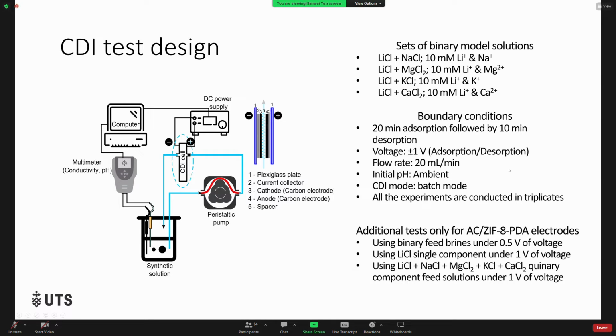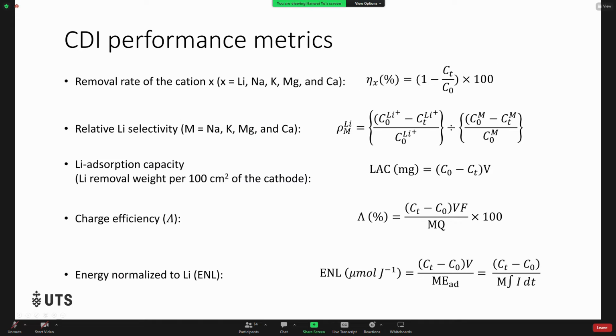These experiments are based on all 3 electrodes, and the additional tests only for the modified electrode are the CDI test using binary feed brine under the voltage of 0.5 volts, and the CDI test using a single component brine and the 5 component feed solution under the voltage of 1 volt. So here are the CDI performance metrics: the ion removal rate, the relative ion selectivity,